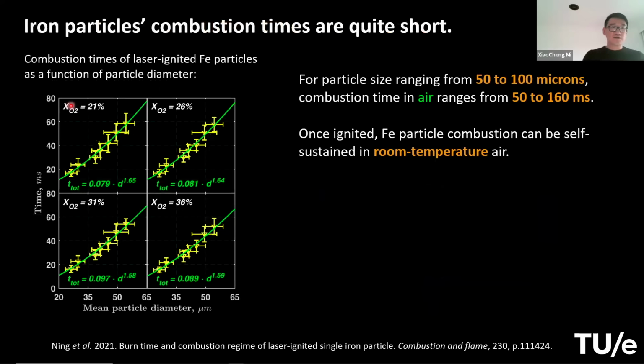But we can see that the iron particle combustion times are actually very short. From Ning et al.'s result, if we burn iron in air, 21% oxygen, the overall combustion time is on the order of tens of milliseconds for these tens of micron-sized particles. If you extend this rate law to larger particles up to 100 microns, which is again the range of practical iron particles in an industrial burner, the combustion time just extends to maybe about 150, 160 milliseconds, which is also not very long.